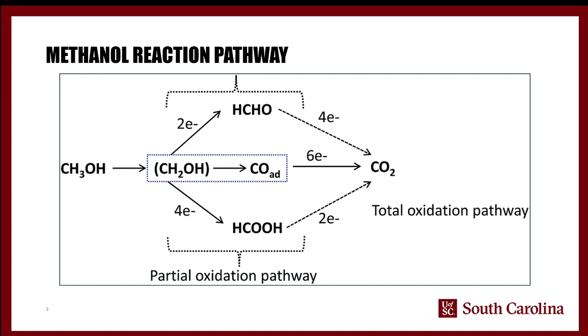So again, this is kind of a more detailed breakdown of the methanol oxidation reaction pathway. Again, you start with methanol. It goes through multiple oxidation steps. But the big issue here is that the CO is sort of the primary one. And when that CO adsorbs onto platinum, your reaction pathway is broken until you can clear that off. And so that's the main issue that we're trying to deal with here.